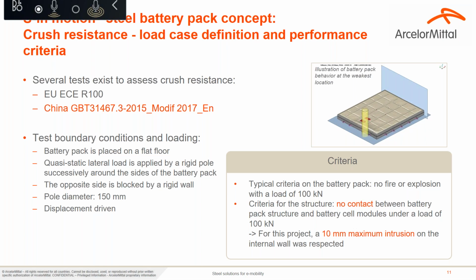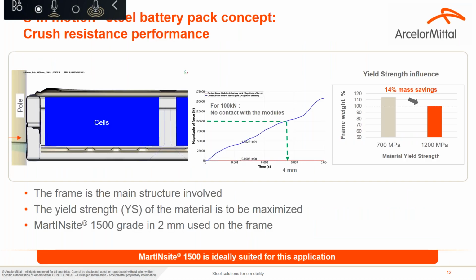We have selected to use finite element analysis with specific criteria to adapt to this test. In our case, we have a very small gap between the internal side of the structure and the module in order to increase the volume of the cells and the range at the end. So you have only a 10 millimeter gap between the internal side and the modules. And the second criterion that we have selected, in order to be very safe, is to have no contact between the structure and the module during this test. We have been working with partners that check, for example, fire resistance in all kinds of conditions, and it's their advice not to touch the cells inside the pack.